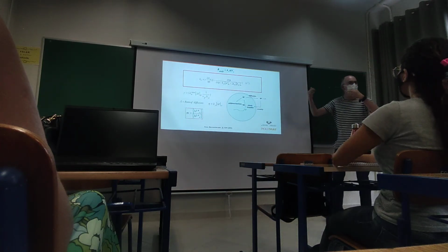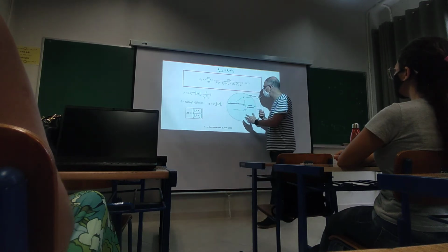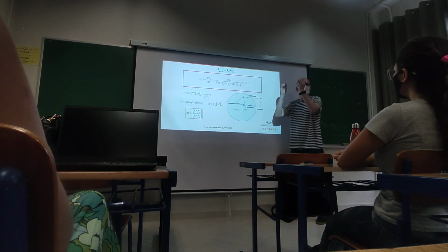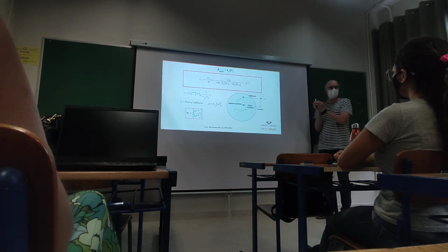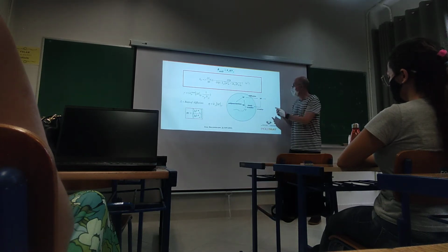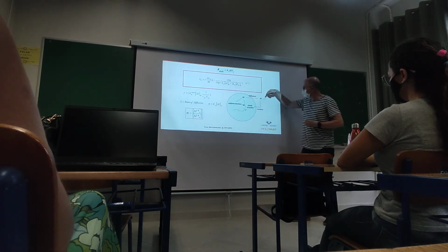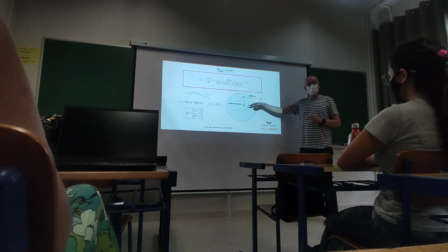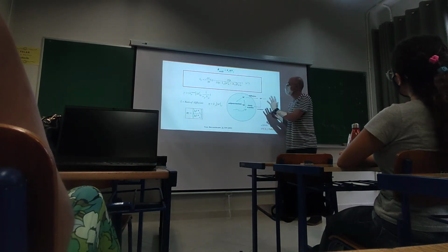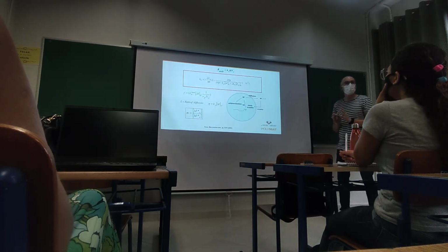So there are all of these terms that I put there, but I think the concept that you should take into account is that not all the radicals in the polymer particle can exit, only monomeric radicals can exit, and that this exit should also take into account that the radicals can re-enter. So taking into account these considerations, you have a desorption coefficient that can be calculated in each case.